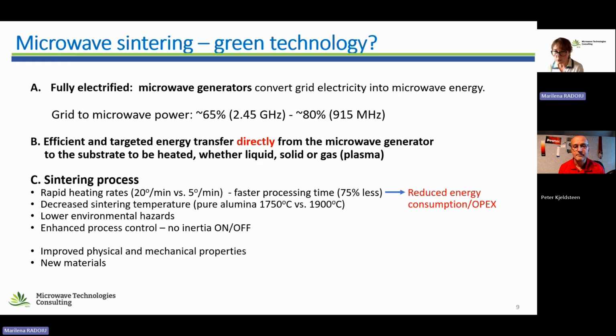Then it's also been reported that because of this very controlled way of applying energy, the sintering temperature can be decreased. I saw pure alumina sinter in microwave at 1,600, 1,750 degrees versus almost 2,000 in conventional. Yeah. There are lower environmental hazards, obviously. We don't burn gas, we don't produce CO2, not directly anyway. And we have quite a lot of process control.